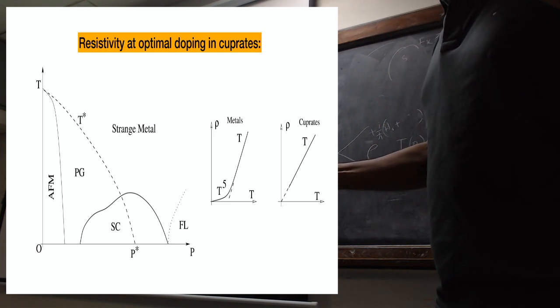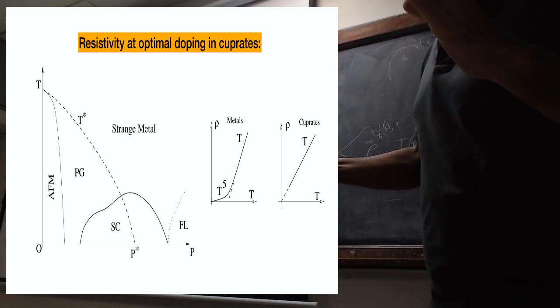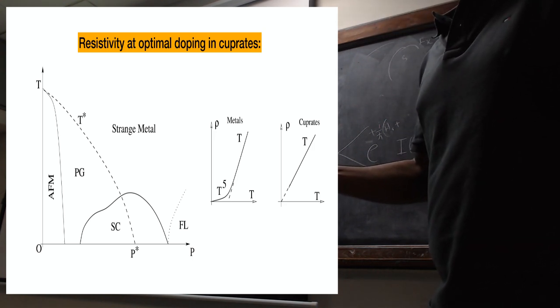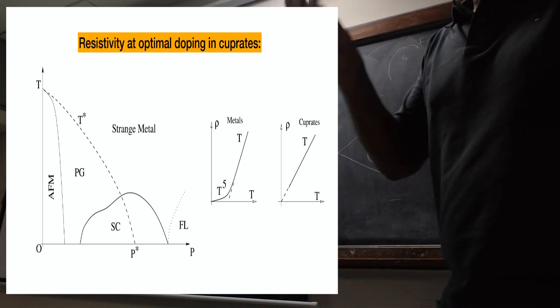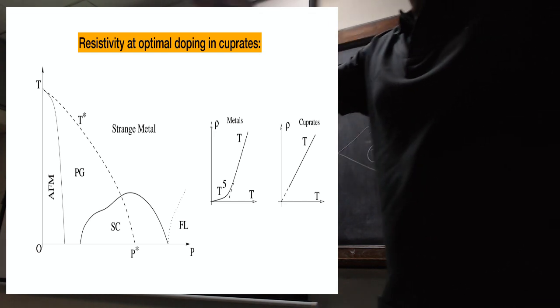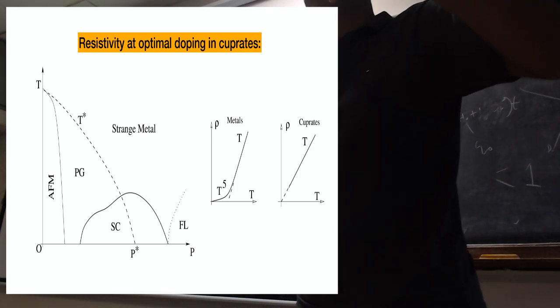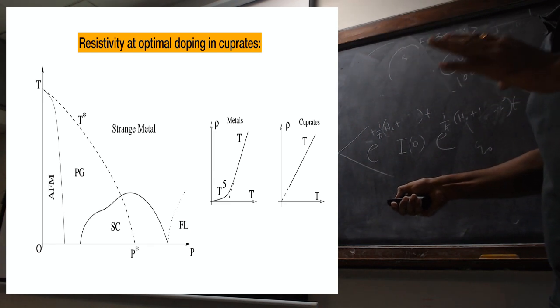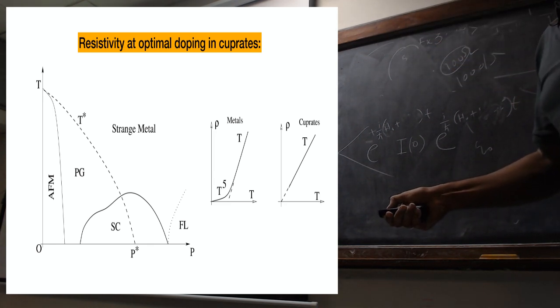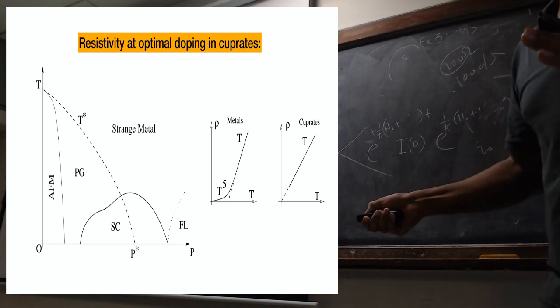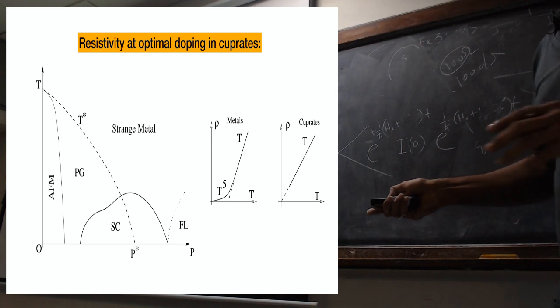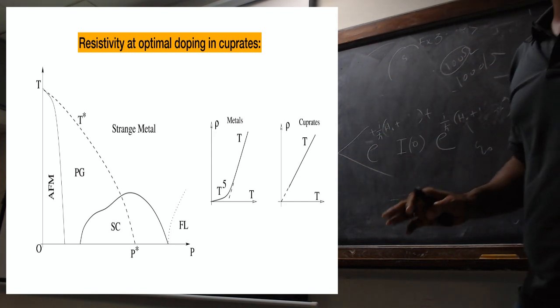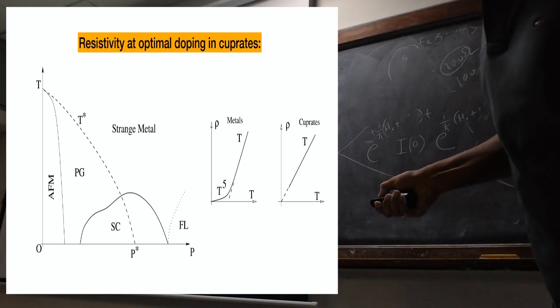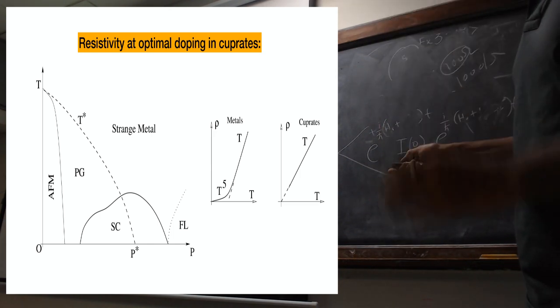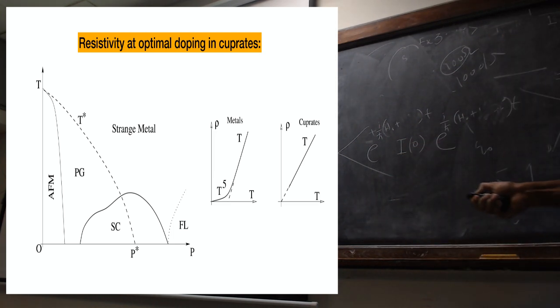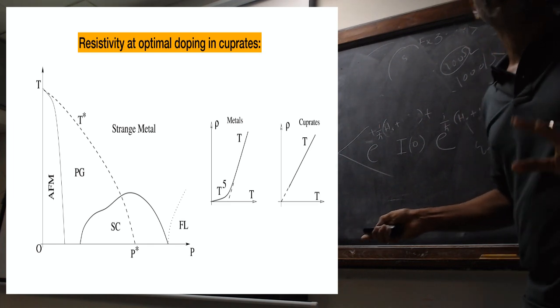So somehow they are magnetic systems. It's an antiferromagnet, but when you dope, it is destroyed. The magnetism is not completely destroyed; it resides at a short length scale. But at P star, something happens to the magnetism. Maybe there are long-range fluctuations. This phenomenon is very important because it's not a property of one material. In cuprates there are hundreds of materials that show this. In heavy fermions also, hundreds of materials show this. So this means that it's a universal law. In the previous picture, the axis is doping. So it is believed that T linear is a universal phenomenon, and it has a universal explanation. That's the question.